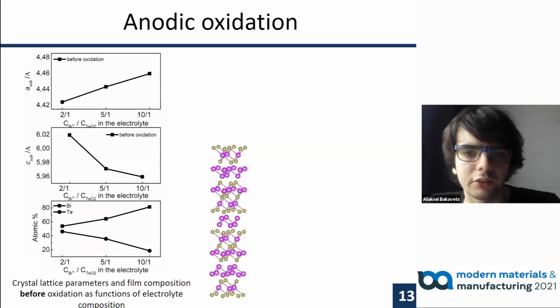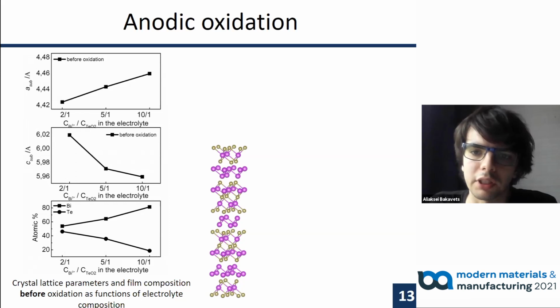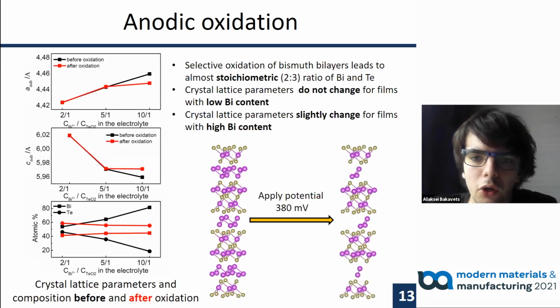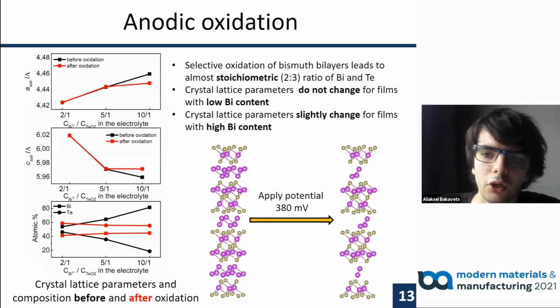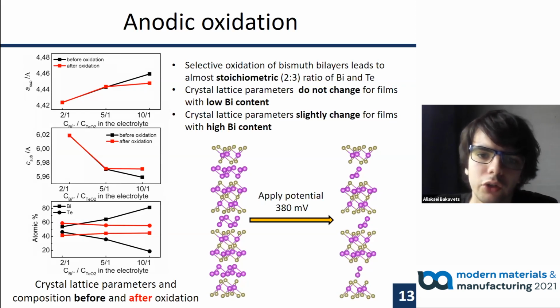We compared the effect of the anodic treatment at the potential of bismuth bilayer anodic oxidation and different bismuth content in the electrodeposited films. The composition of films almost corresponds to Bi2Te3 after oxidation, while lattice parameters were not affected by the oxidative treatment, except in the case of very high initial bismuth content.